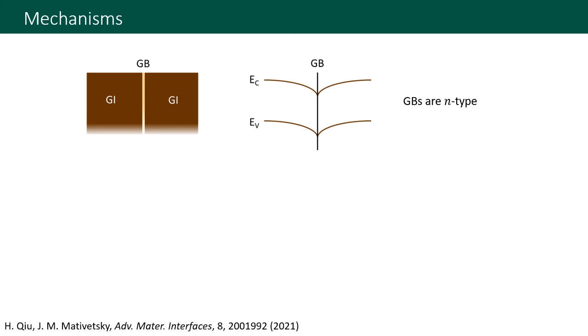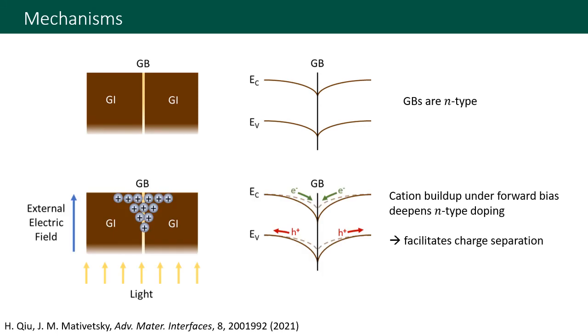The observed light and voltage-induced cation motion can play an important role in optoelectronic device operation and degradation. Regarding the elevated open circuit voltage at grain boundaries, we attribute this to two effects: first, the increased surface potential at grain boundaries is associated with n-type doping and local downward band bending; second, cation accumulation at grain boundaries can deepen local band bending. This band bending can locally attract electrons and repel holes, leading to reduced charge carrier recombination and an increased open circuit voltage at grain boundaries.